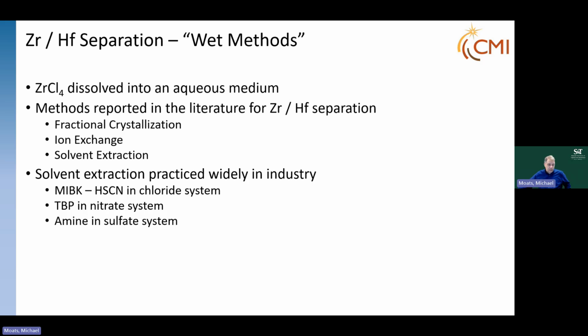In solvent extraction, the United States uses the chloride system. So we dissolve the zirconium tetrachloride and hafnium tetrachloride into a chloride-based system, and then we complex it with thiocyanate and do solvent extraction with MIBK. In India, they dissolve it in a nitrate system and use TBP. In Japan, they use a sulfate system and use an amine to do the solvent extraction. So again, lots of fun chemistry, lots of different ways to do this.